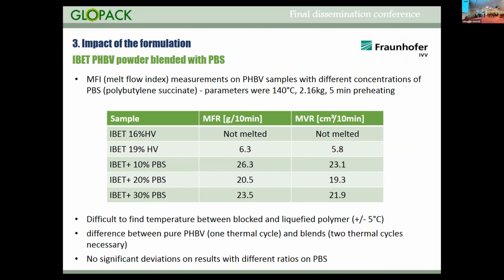So the last question was the impact of the formulation, which I forgot to mention in the presentation. You see in the state of the art, if you increase the HV content, you decrease the crystallinity of the materials. So the assumption was, if we decrease the overall crystallinity, the blending with other biopolymers will be easier, because the amorphous phase is more important, so you can more easily blend with other materials. That is why this strategy was also investigated in the project.